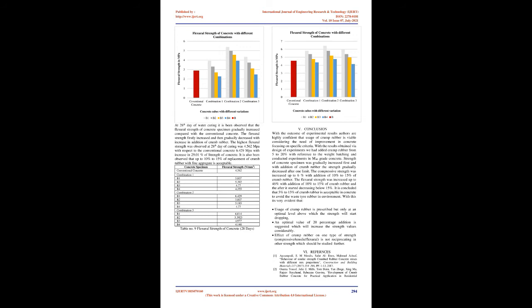At the 28th day of water curing, it has been observed that the compressive strength of the concrete specimens gradually increased compared with the conventional concrete. The compressive strength first increased and then gradually decreased with increase in addition of crumb rubber. The highest compressive strength observed at the 28th day of curing was 55.98 MPa with respect to the conventional concrete at 52.72 MPa, an increase of 5.9% in strength of concrete. It has also been observed that up to 10% to 15% replacement of crumb rubber with fine aggregate is acceptable.